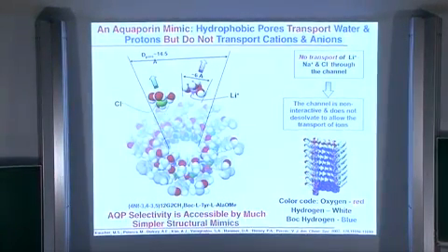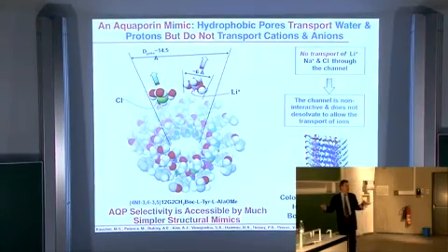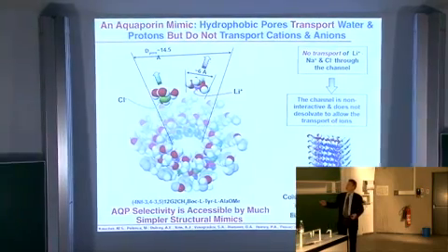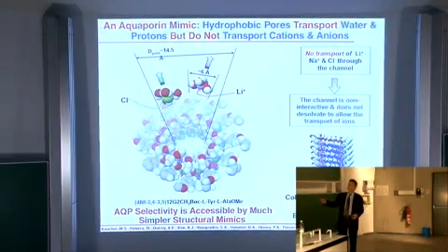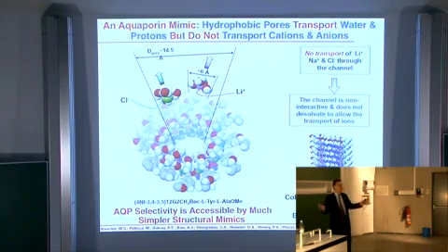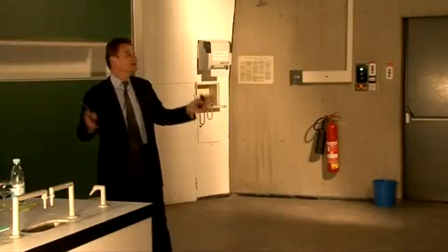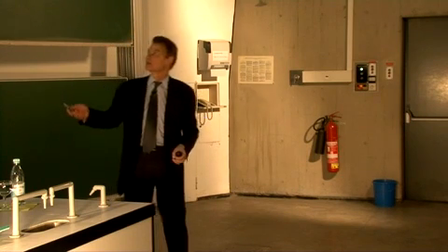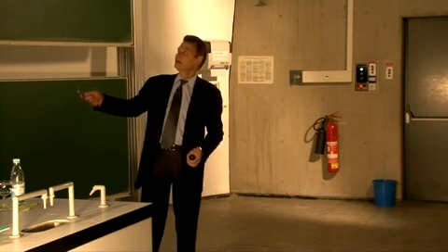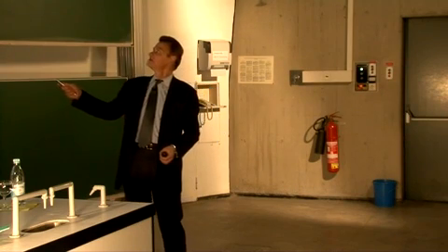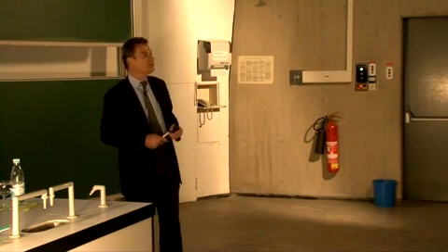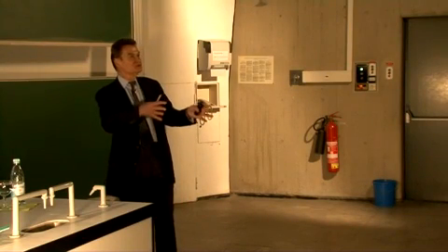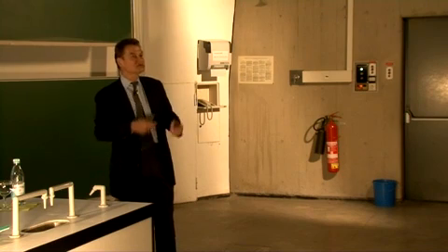NMR on lithium and sodium and chloride, and check for the ion transport. And to our surprise, in spite of the fact that the pore size is 14.5 angstrom, there is no transport. And that tells us a lot of information that is very hard to obtain by structural biologists. You don't really care about the pore size. Even if these ion pairs are solvated by water molecules, they are recognized by this structure, because transport through channels requires desolvation.